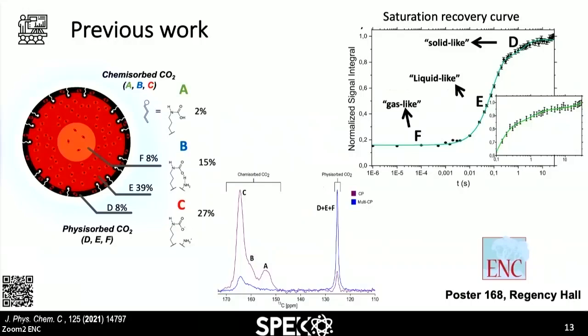So in the previous works I've shown you, we have focused on the chemisorbed portion of the species that are formed. However, the physisorbed species usually dominate the spectra. And in this particular work, we have tried to not only quantify, but also characterize the physisorption. And it is more difficult because, as you can see, at least this is the chemisorption portion, and you can see that the chemical shifts are slightly different. But as you observe the physisorbed portion, you see that they fall in the exact same chemical shift.